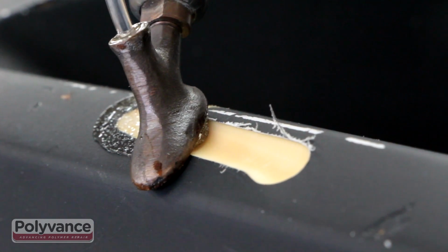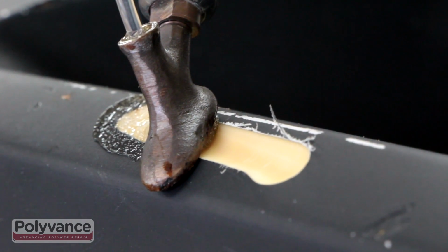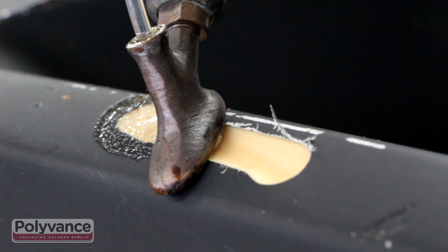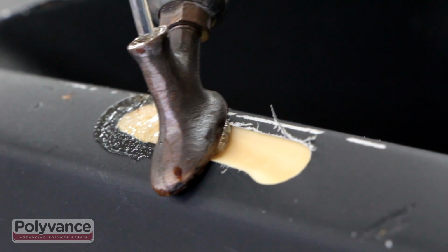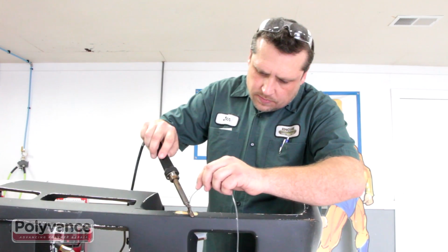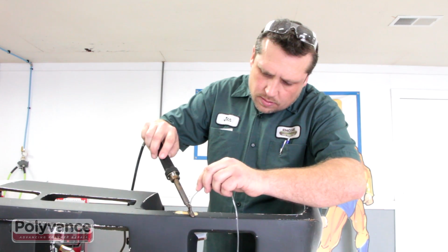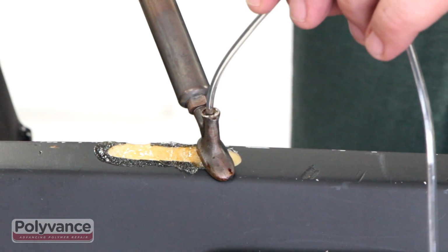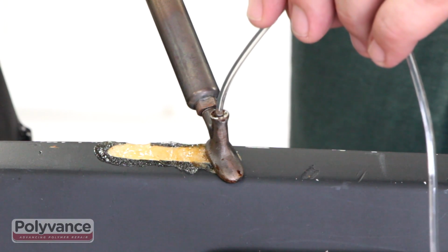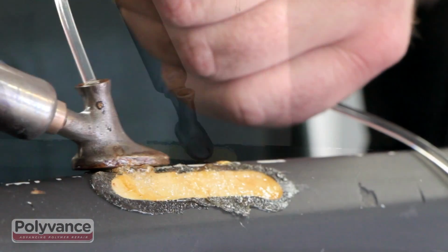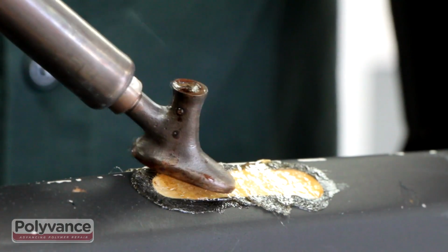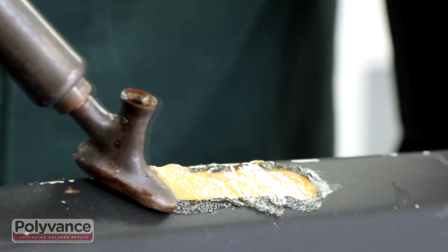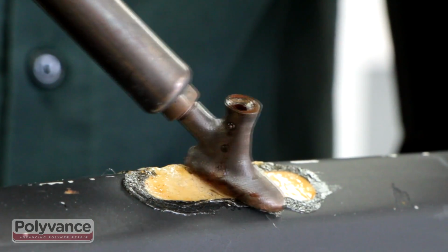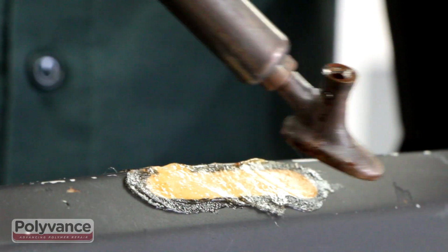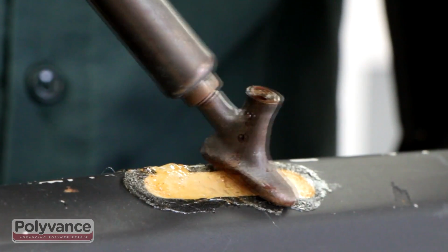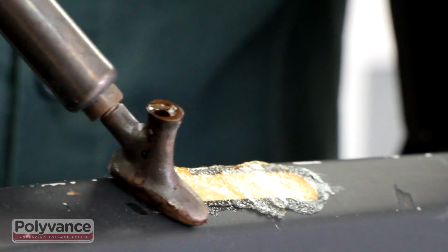Note that the welding rod itself is a thermoplastic urethane, so it melts. It has very good adhesion to thermoset urethane. Note that we are not trying to melt the base material. Just melt the welding rod into the V-groove. You can touch the bumper with a hot welder tip, but don't linger the heat or try to melt the bumper itself. Just press the melted welding rod into the pores of the plastic and press out any remaining air bubbles. Use the welder's heat to smooth the surface of the welding rod.